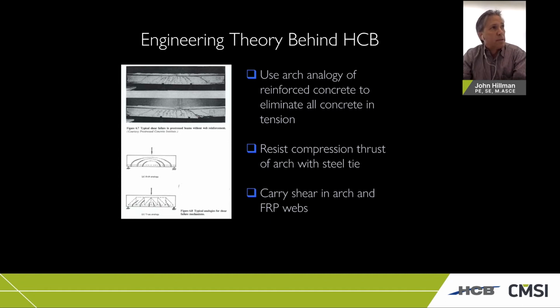So the impetus of this really came back from, like I said, I'm a practicing bridge engineer, and we think about the theory of reinforced concrete. We know that all the concrete that's in tension is going to crack, and basically it's holding the reinforcing steel in place. It's holding the shear reinforcing, the tension reinforcing. But you're going to get flexural cracks and shear flexural cracks that essentially result in like an arch analogy or a truss analogy, where we know there's a compression load path that's going to carry the applied loads over to the supports. So the whole idea behind this was, can we develop a beam where we get rid of all the concrete that actually doesn't serve any purpose?